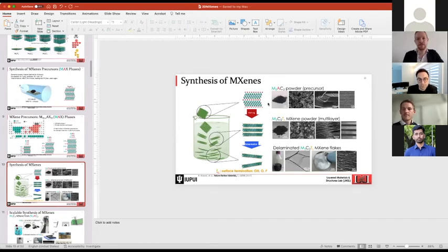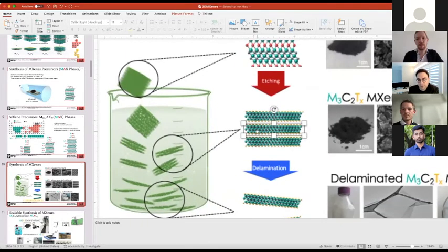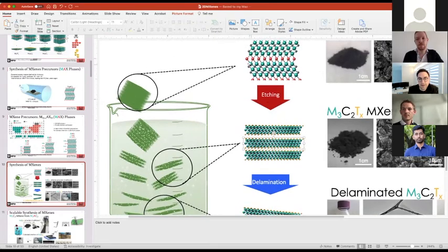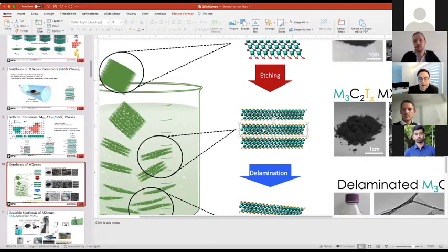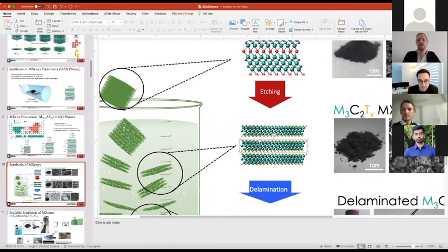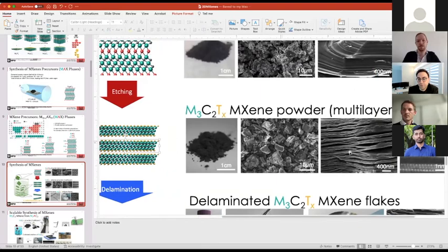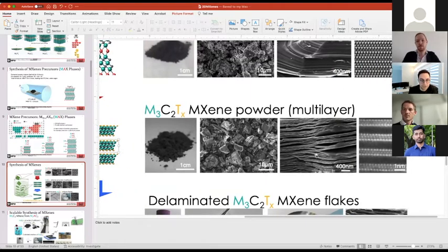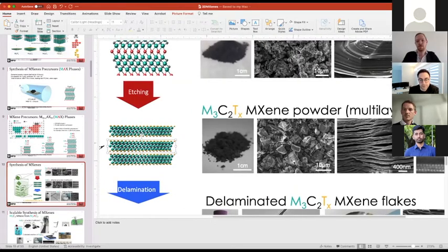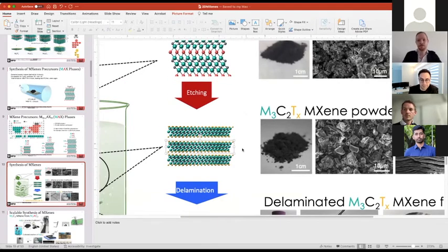When we leach out the aluminum, then the surface titanium, for example, is available to bond. The leaching out usually is by attacking fluorine ions to aluminum. Then the fluorine and oxygen will also attach to the surface transition metal, and that will create these surface terminations. These will now have bonding, but not the primary metallic bonding anymore. They will have the secondary van der Waals bonding, or hydrogen bonding if we have OH on the surface. With these surface termination interactions, they will be forming these layers still within one powder structure. So they're still in a powder. They don't really repel and go away by just leaching out.